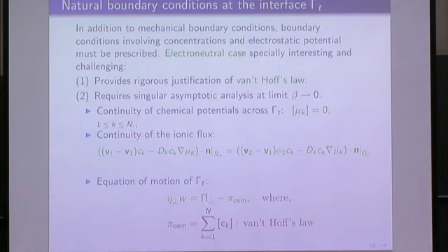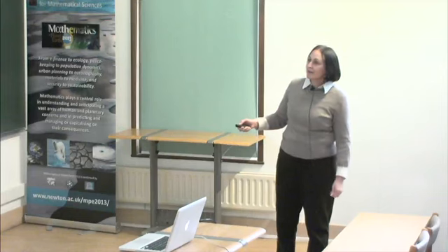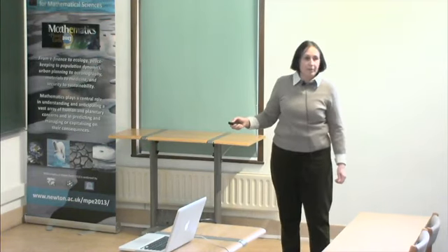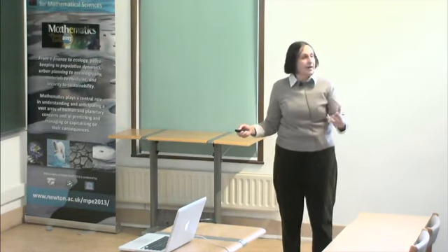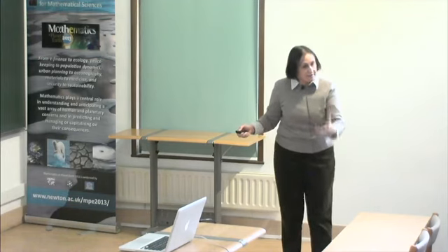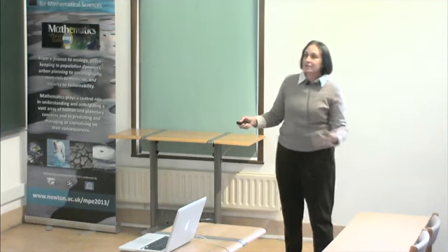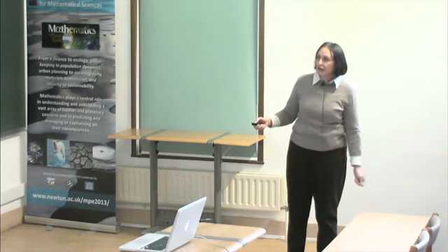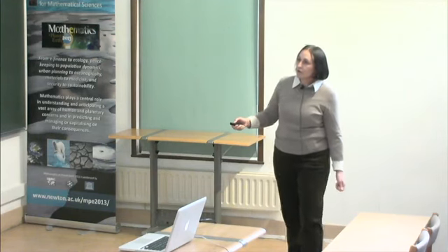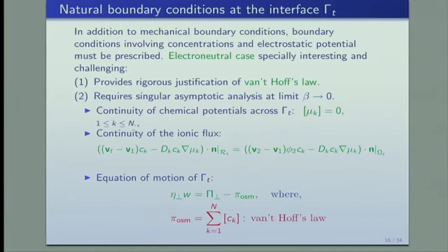Now, when we do the dynamical coupling, we inherit this extra force, which is the mechanical force. Also, our singular perturbation analysis reproduces Van 't Hoff's law, which says that the osmotic pressure, in other words, the pressure that is inside because of the fact that there are these ions, is really the sum of jumps in concentrations. So we're able to rigorously justify how the mechanical force really contributes to Van 't Hoff's law.